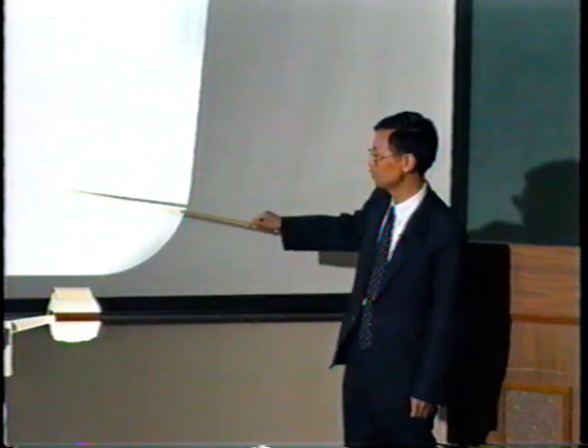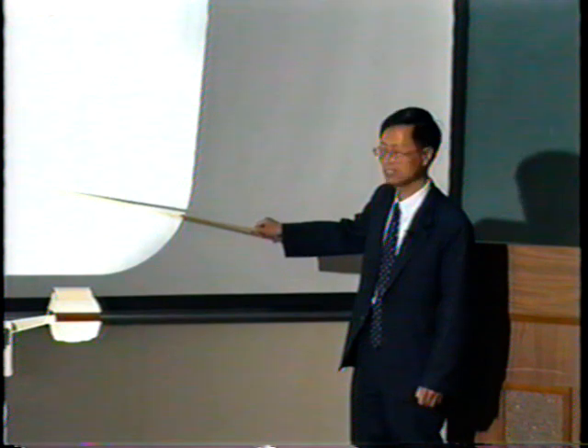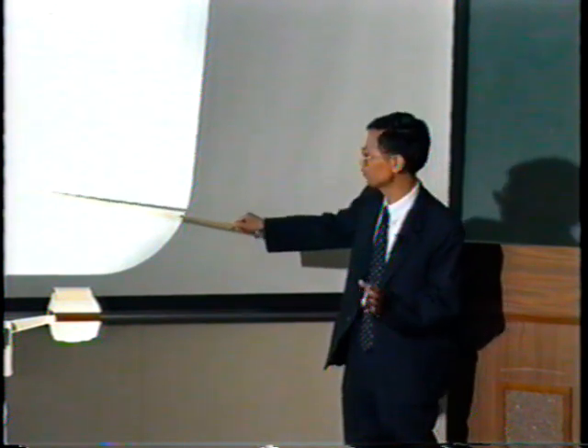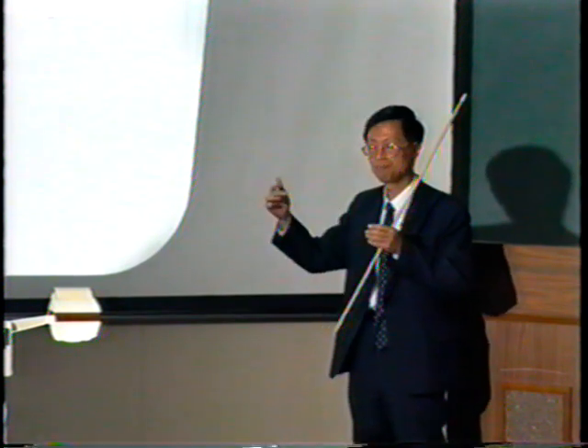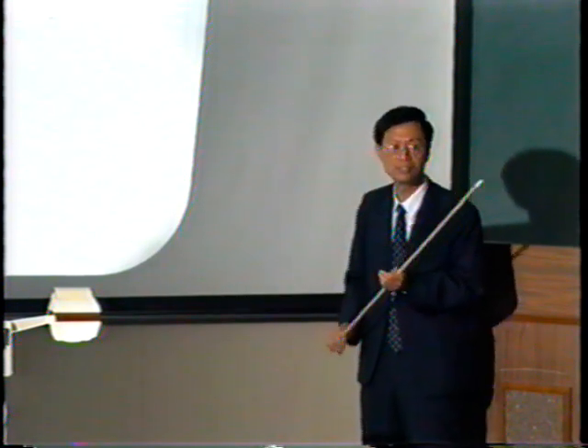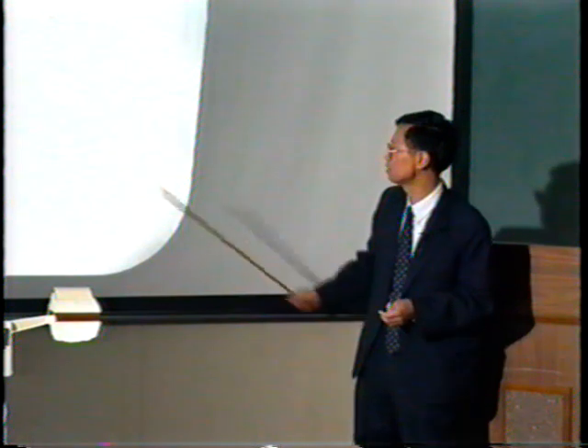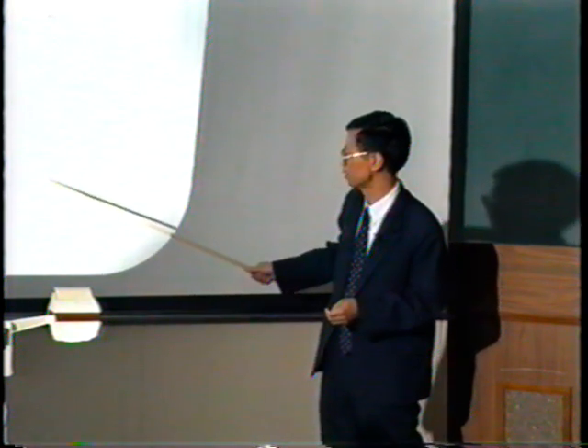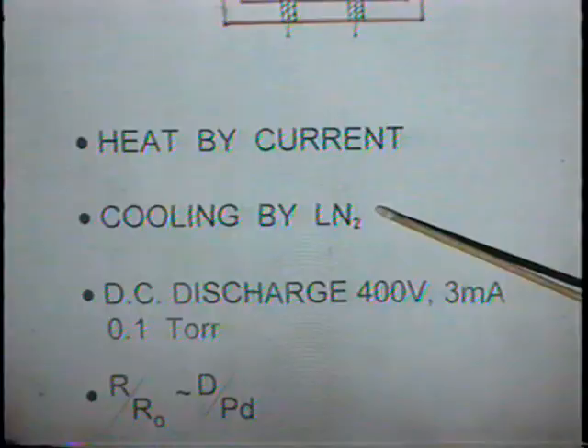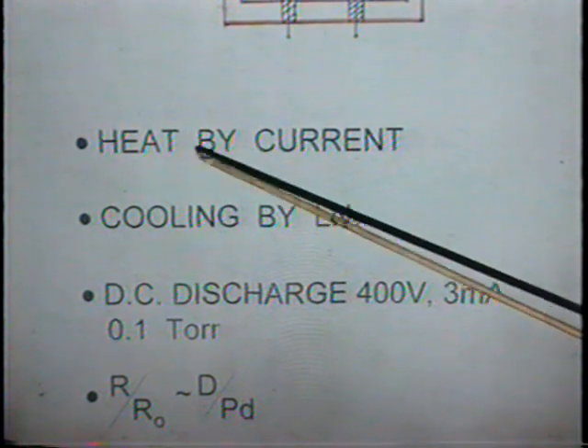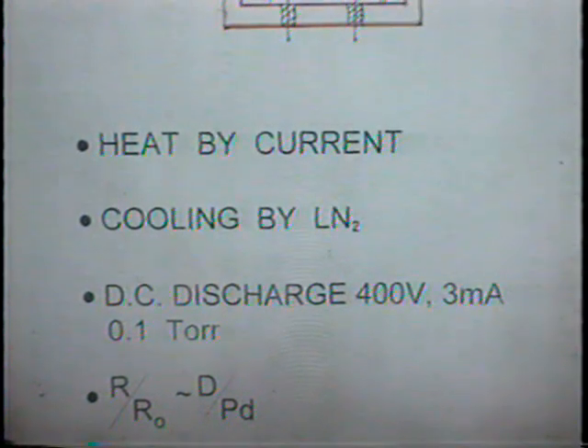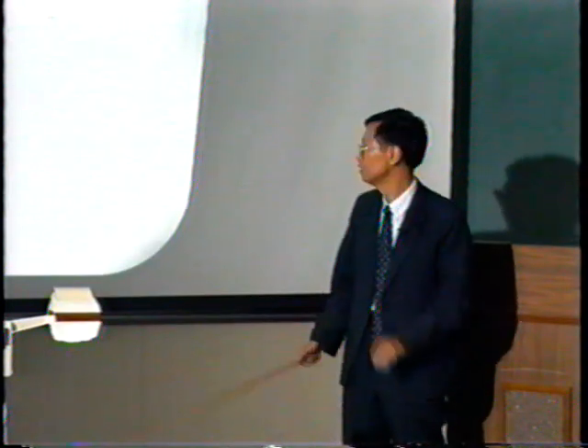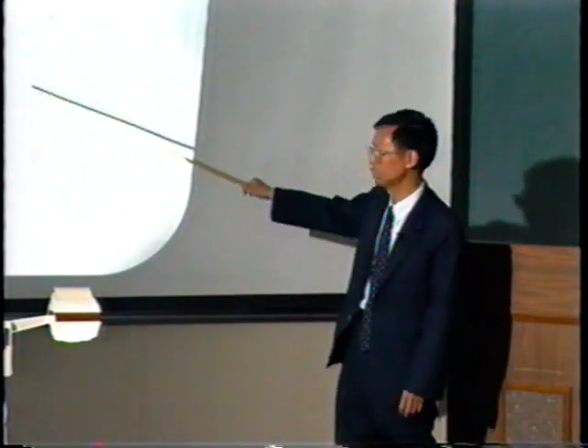Why do we do the cooling? Because we expected that cooling down to the liquid nitrogen temperature might give some tunneling to increase the diffusion coefficient and increase the loading ratio, but it didn't appear. With heat, constant heat doesn't work very well, but finally we found that pulse heat will change the loading rate. So I will talk about this.